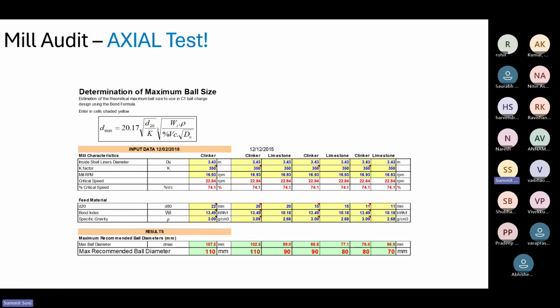The maximum ball size will typically represent around 10 to 20% of the total charge by weight. So when you're calculating the D max, that will be around 10 to 20% of your total weight of the ball charge. You will need a gradation of smaller balls below the maximum size. Let's say the first gradation will be 40% of the maximum size, 30% next size down, 20% again next size down, and 10% of the smallest. This is for chamber 1.